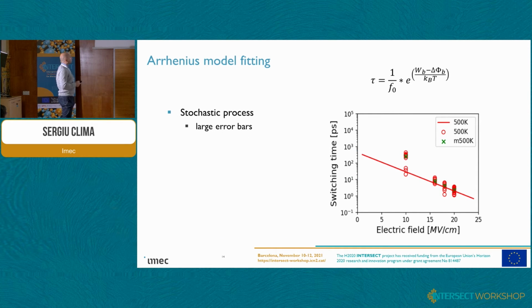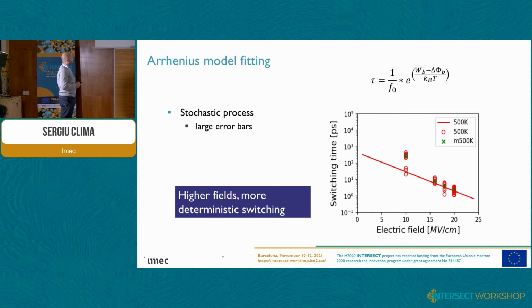We tried also to see whether we can fit it with Arrhenius, and in this particular case, at high electric fields, they do fit the Arrhenius behavior, but then we have strong departure from Arrhenius at lower electric fields. This is quite known from other memories out there, where the Arrhenius behavior is quite approximate.